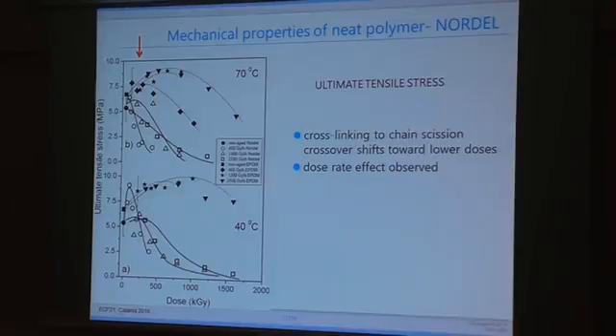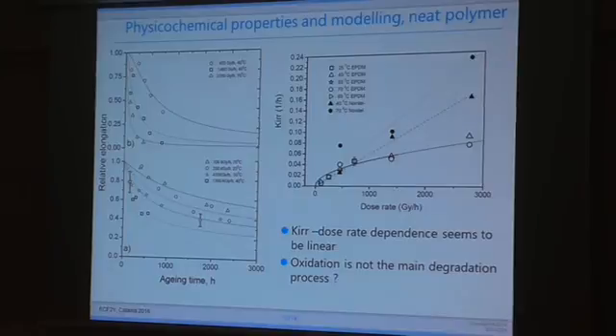prevent diffusion of oxygen. Further on, we applied the same model to study the elongation at break data of the neat polymer, and now we don't observe this square root dependence anymore. Now the dependence of this constant versus dose rate is more linear. So this brings us to a question: is oxidation still the main degradation mechanism in the neat polymer? Again, in order to analyze this further, we need to do some additional chemical testing.